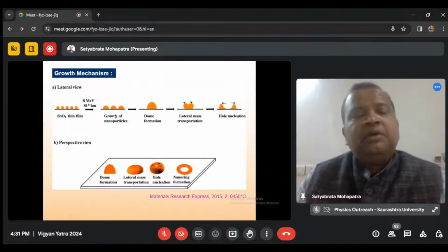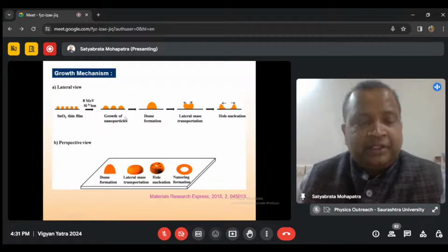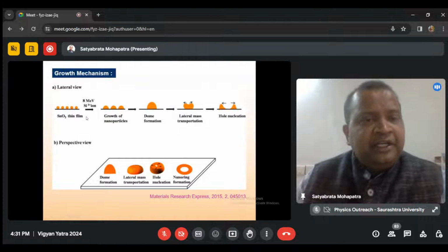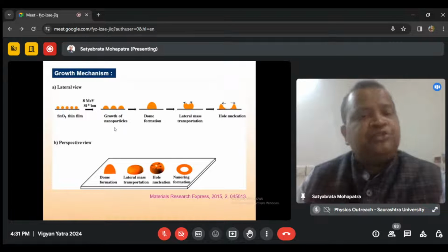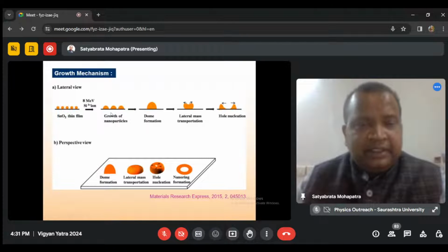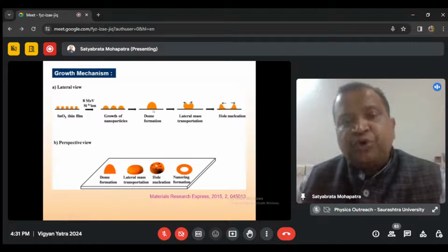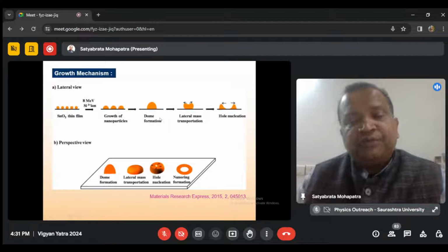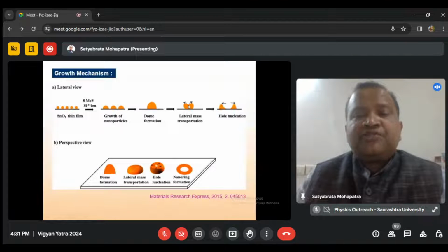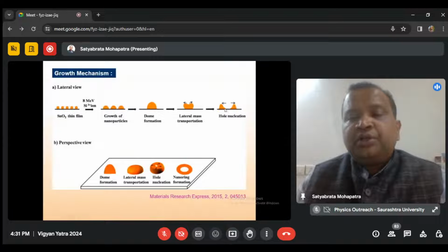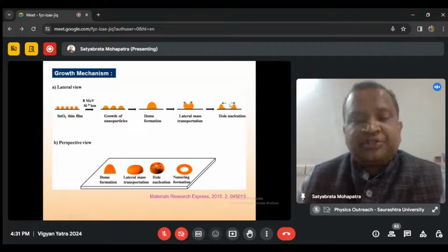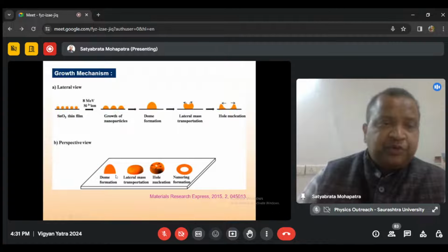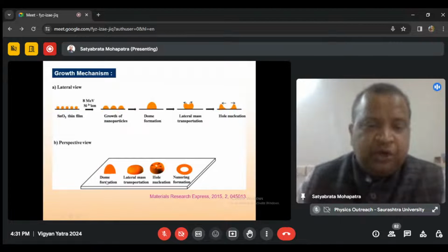Now, we propose the growth mechanism, which was published in Materials Research Express. When you irradiate this nanostructured tin oxide film, in the first phase there is growth of particles, because these 8 MeV silicon ions deposit a good amount of energy in electronic excitation into the film, which leads to the growth of these nanoparticles. This growth further produces dome-like structures sitting on the substrate. However, if you keep on increasing the fluence, then there is lateral mass transport, and it produces hole nucleation inside these structures. So if you see from a perspective, you can see that this dome formation is there.